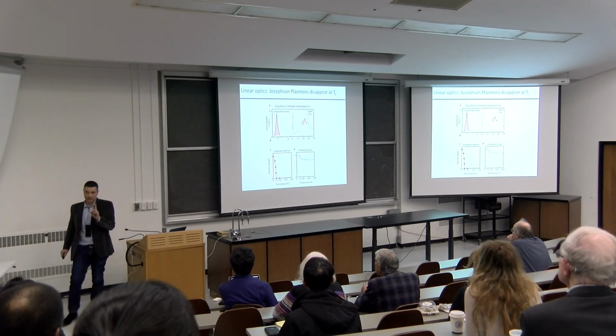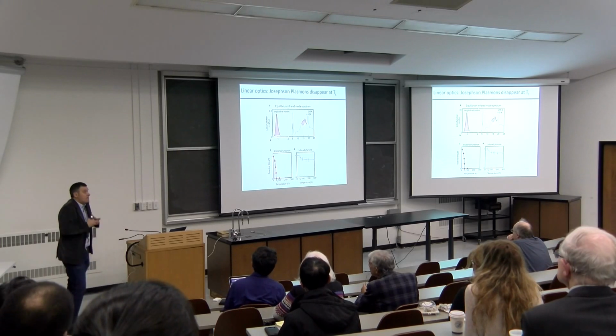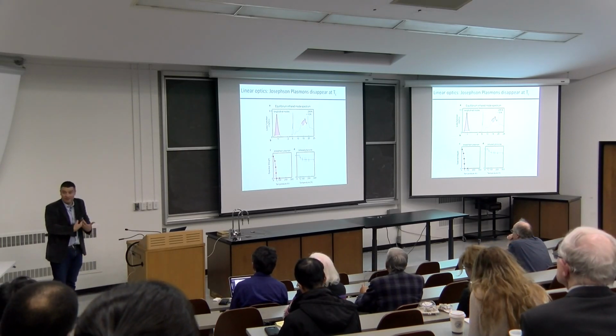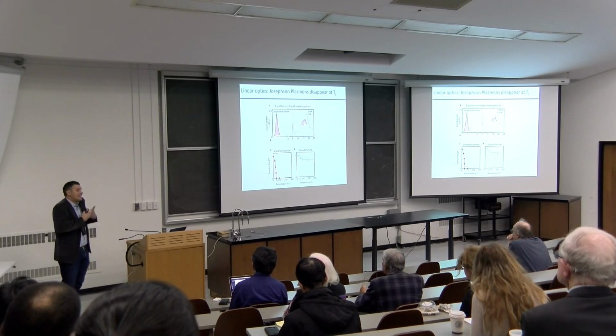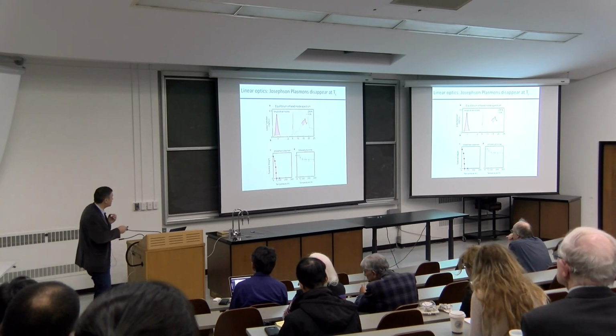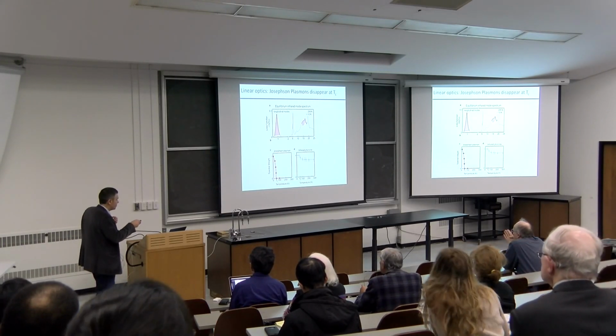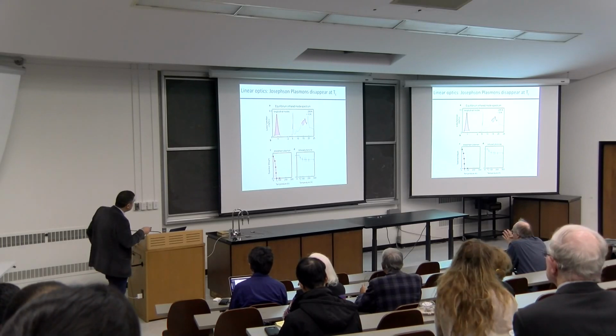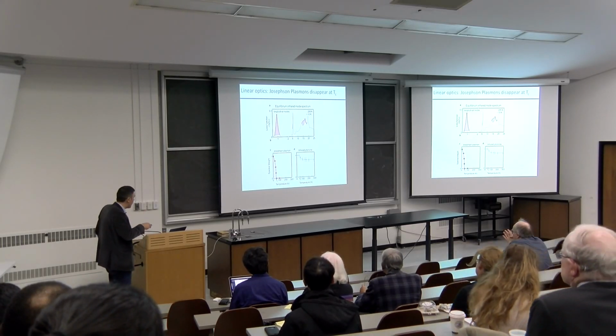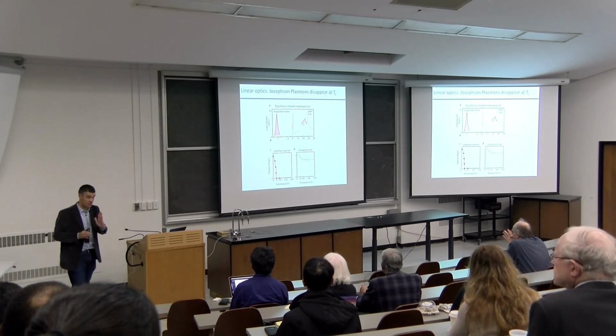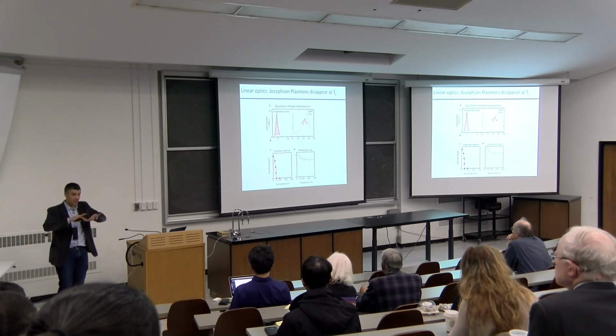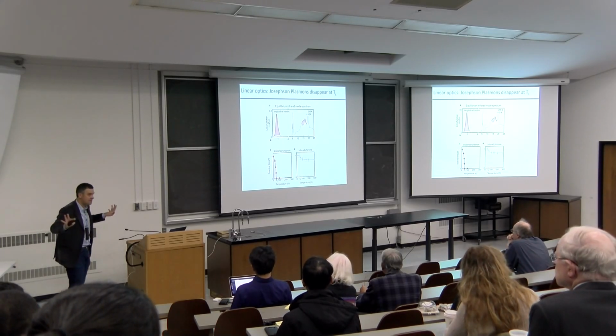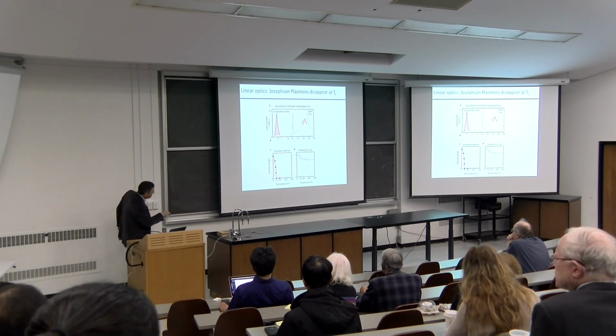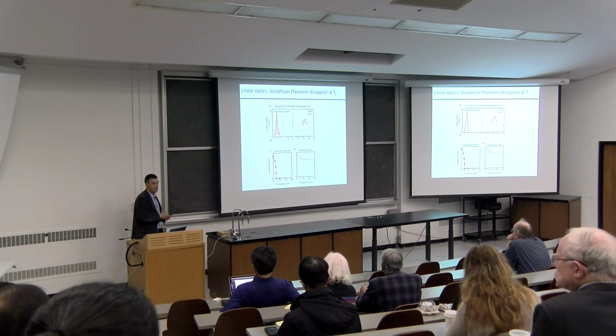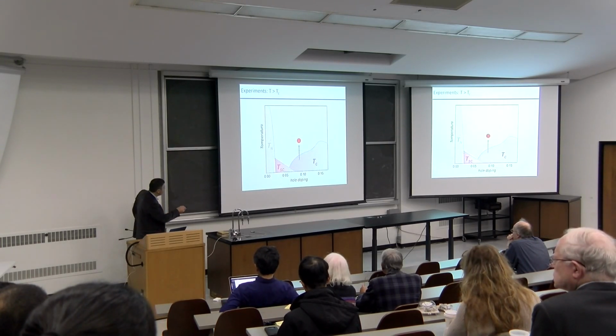Now, one more important point. Because my three-wave mixing process, amplification of the superconducting order parameter, is happening, I would expect this effect to go away at TC, because I know that this is an equilibrium spectrum. This is the loss function where I see all the zero crossings. I know that this specific Josephson plasmon in equilibrium goes away at TC exactly. At k equals 0, which is where I'm measuring, the Josephson plasma fluctuations with correlation lengths of 300 microns at 1 terahertz disappear exactly at TC. And this is very different from all the other phonons, which really continue all the way. So in principle, if I redo the experiment in the normal state, my three-wave mixing signal should go away.